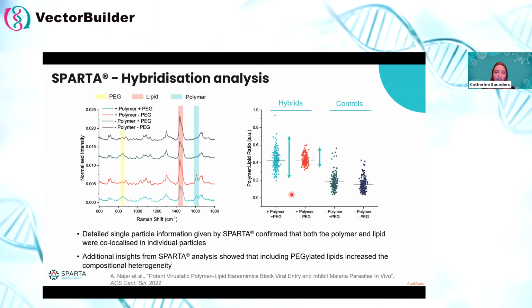What's also quite interesting, and one of the reasons we really like this single particle analysis, is that we could detect a difference in heterogeneity based on the formulation. As a side observation, you can see that in the formula without PEG, this was a nice tight distribution, but including PEG increased the compositional heterogeneity of these particles. It increased the spread of the polymer signal that we were seeing. What I'll say is that in this case, this was the first study just to really understand hybridization. So this was just a nice observation.